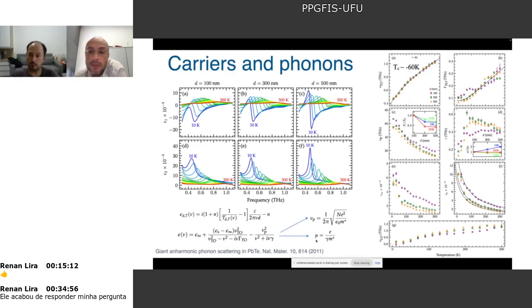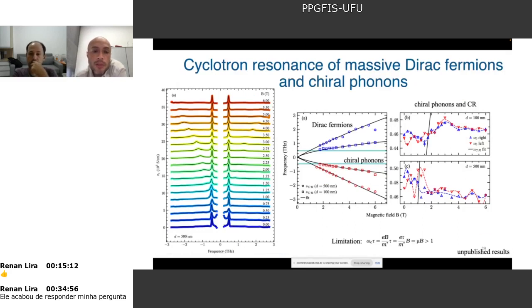So you can see here that in a single measurement, we can characterize carriers and phonons: the frequency of the phonon, the width of the phonon, carrier concentration, and mobility. And this is a measurement of mobility without using any electrical contacts, which gives you a very clean measurement. Also, if you put these thinner films in a magnetic field, we observe cyclotron resonance, as in the paper that I showed you at the beginning in the introduction. So this peak here that almost doesn't move is phonon absorption, and then here you can see the absorption from cyclotron resonance, in left and right-handed also.